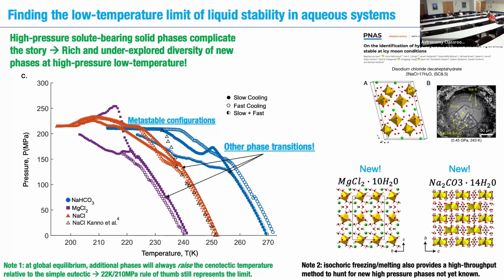So this shows NaCl, NaHCO3 and MgCl2, right? And in all of these, we detected new phase transitions that generally had not previously been reported, which was fascinating. The timing was really good for the first of these. Baptiste and Steve and co just last year had this brilliant PNAS article where they found a couple of new phases of high pressure hydrated NaCl. You think about water-NaCl, one of the most studied phase diagrams on the planet in history, and yet they go to low temperature, high pressure, and find all this crazy new stuff happening. So we were able to confirm Baptiste's earlier findings with this transition that we observed here. We confirmed the pressure at which he had estimated that this SC 8.5 phase should emerge.